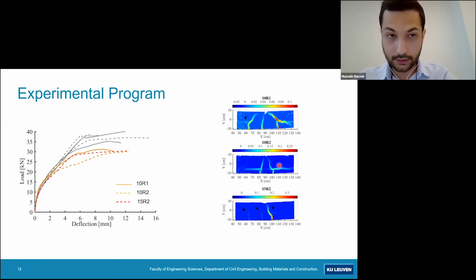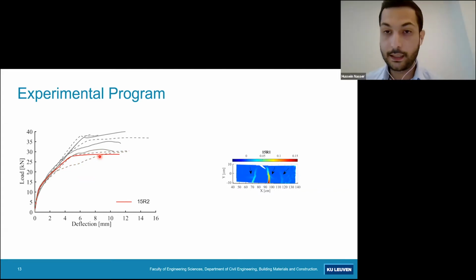If I also relate the bond deterioration to the load deflection curves, for beam 10R2 the severe formation of splitting cracks is translated into a load deflection curve which is the least stiff. Therefore, taking into account the bond deterioration is important to be able to predict properly the reduction in stiffness of corroded beams. Going to the beam that reached the highest corrosion level, it reached 13% of mass loss. The beam failed by yielding, but it didn't show formation of excessive splitting cracks. Therefore, it's possible that a higher corrosion level doesn't necessarily mean a higher level of bond deterioration.